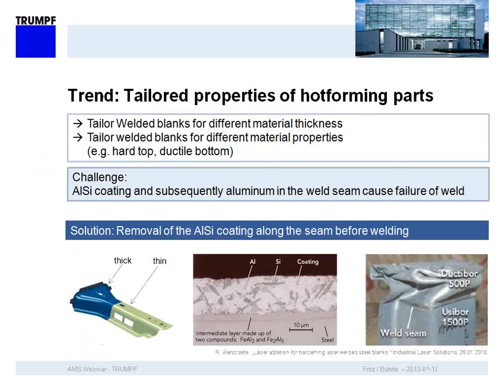So I want to outline one trend which we can see in hot forming: OEMs are using tailored hot forming parts. That means they want to bring the fuel consumption down, and consequently they have to reduce the weight of the car. That means they use the thickness of the material only where they need it, and in other areas they use thinner material, which can be done by roll forming, or one of these applications is tailor welded blanks. Tailor welded blanks with aluminum silicon coated steel are quite a challenge, because the aluminum silicon coating in the welding seam area is not helping.